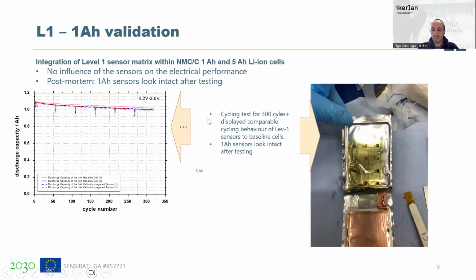Okay, after that, we started the first validation phase with 1 ampere-hour cells. So we cycled the cell at 25 degrees for 300 cycles. And as you can see here, in red, we have the cell without any sensor, and in blue, the cell with sensor. So we have two baseline cells and two cells with sensors. And the evolution of the cell is quite similar with and without sensor. After that, we also opened the cell, and we saw that it is in good condition. The sensor is in good condition. So it seems that the electrolyte did not affect the sensor element.